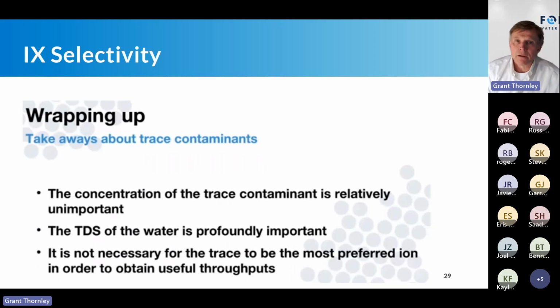So the takeaway on the ionic selectivity is that the concentration of the trace contaminants is relatively unimportant, considering that they're a small concentration in the eluate. The ion exchange has a high ionic concentration. What does affect the selectivity is the TDS of the water. It has profound importance on the efficiencies of that. So it's not necessary for trace contaminants to be the most preferred ion in order to obtain useful throughputs.